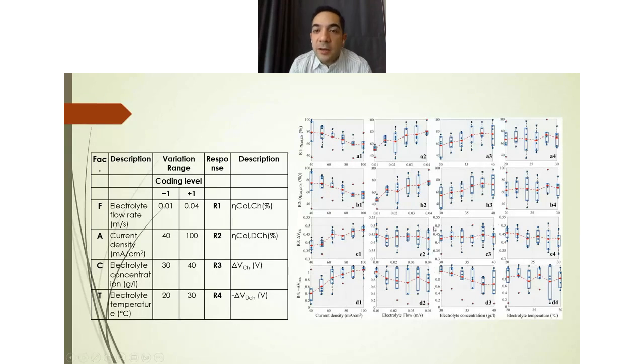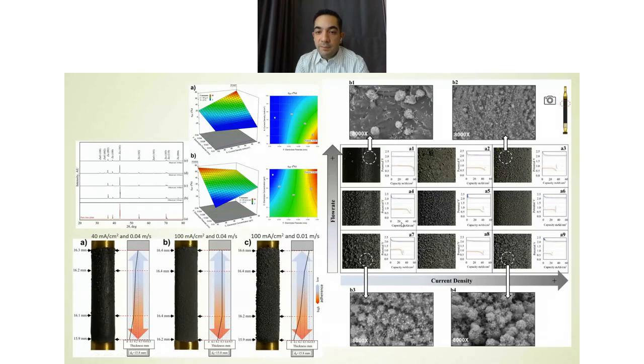The paper also dedicates some results regarding the morphology of zinc as different flow rate and current density have been applied to the system. For example, if you look at this graph on the right, you can see that when low current density has been applied in integration with low flow rate, the morphology is quite mossy and loose. But when you increase the flow rate at lower current density, you can see a very smooth surface here. And the combination of high current and high flow also gives a very good morphology with high adhesion to the surface and less dendritic as compared to low current density.